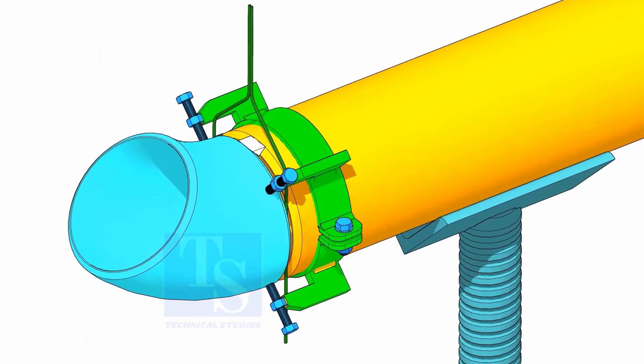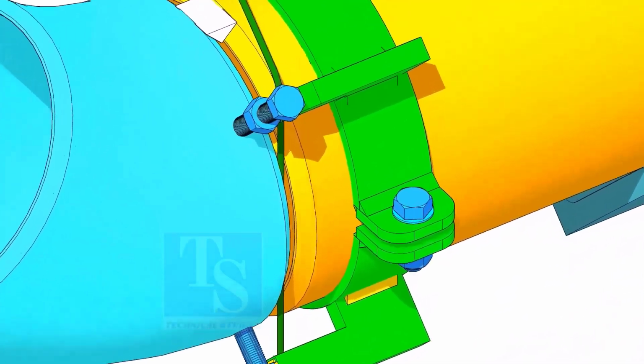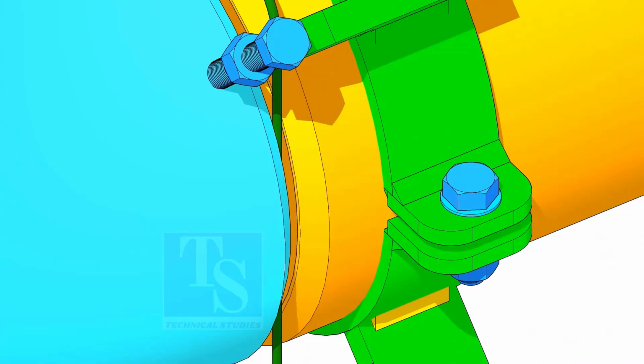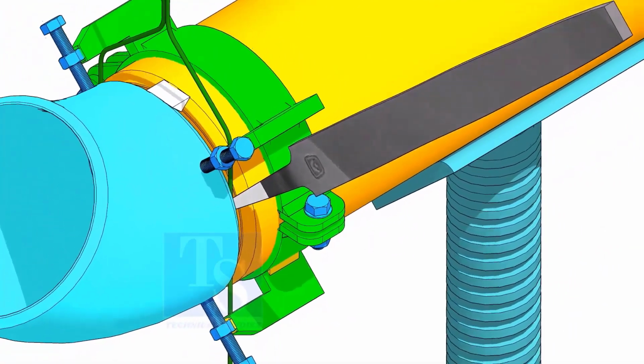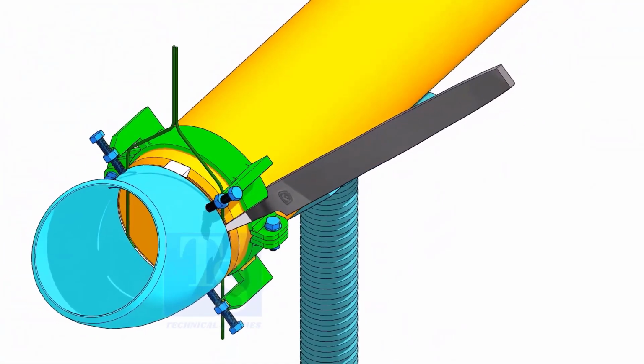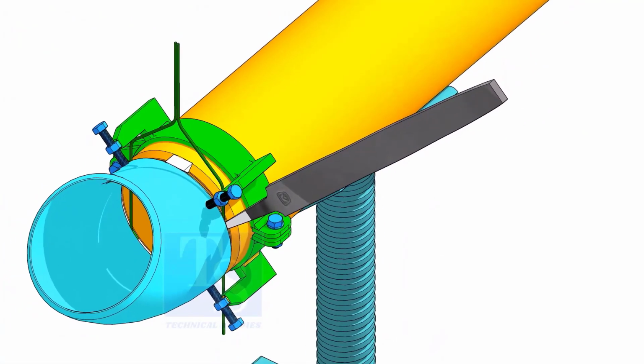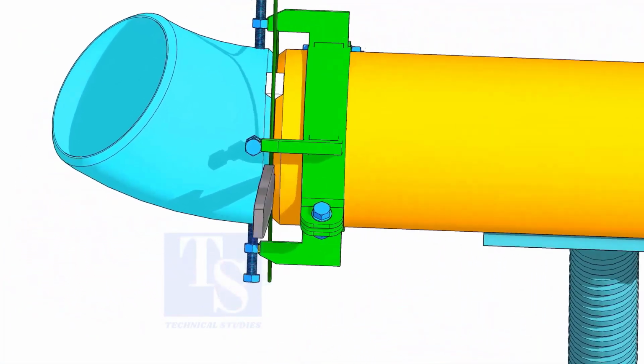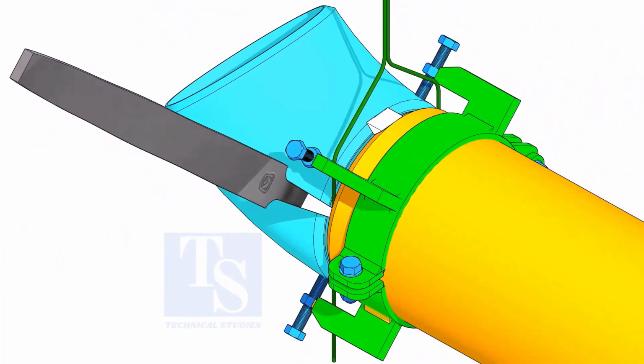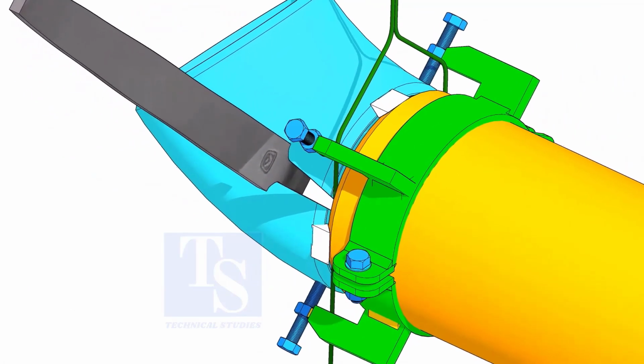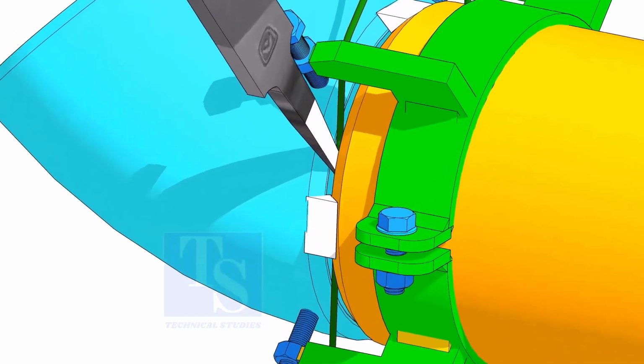All of you know how to use the clamp and the gap rod. During tacking, you can use the file to rotate the fitting and adjust the gap. You would have observed, after a tack weld, the fittings come closer and the gap reduces. Hold the file end in the joint, as shown. This will prevent the fittings from coming closer.